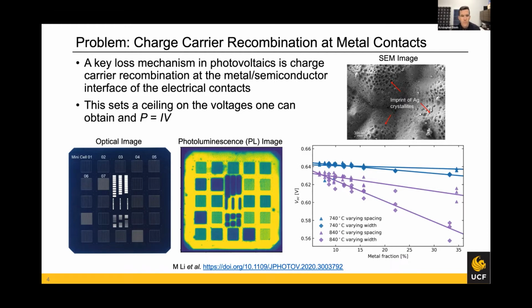Dr. Li, a postdoctoral researcher in my group, has done a lot of work looking at establishing different test structures with these wafers. We do something called photoluminescence imaging, where we essentially get a map of the local voltage. And then you can see how, as you change the metal fraction, depending on the processing conditions, you can end up dropping the voltage of the device, and power equals current times voltage.